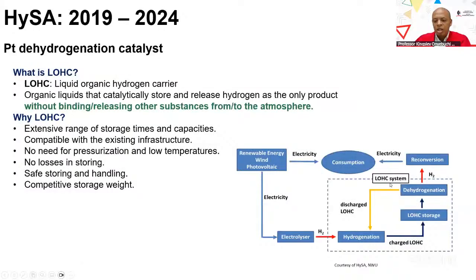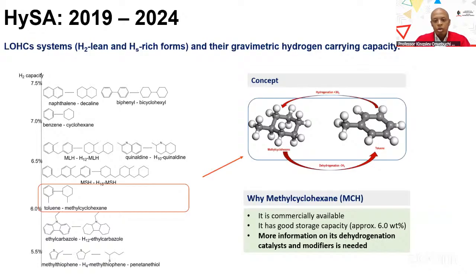mention is that we have a dehydrogenation part and a hydrogenation part. The catalyst for hydrogenation is very cheap, so this is not an area where a lot of research is happening, but the dehydrogenation catalyst is mainly platinum and platinum group metals, which is kind of expensive. So we need to always improve the activity as well as the selectivity of this. For a lot of the work I did back then, I looked at toluene.